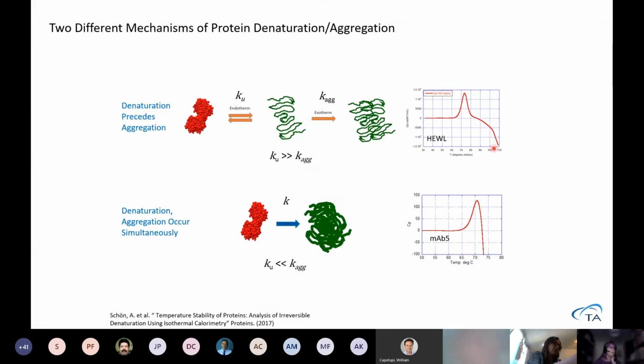So this is a DSC run. And then you can have a reaction where the aggregation occurs simultaneously as the denaturation. And then you will see this type of curve where it goes right down after. You actually don't know where the peak top is to be able to relate the TM in this case, because this reaction could be much bigger than the actual denaturation.